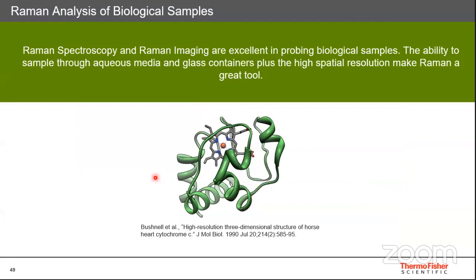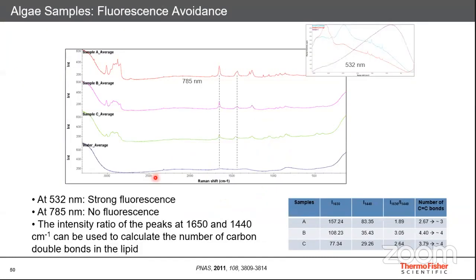Well, it has also been used, as I said, for biological analysis, even if it's an aqueous solution. Here is an example of an algae sample which has shown fluorescence. Here they used earlier the 532, which shows a strong fluorescence. So they have to go to the higher wavelength laser, that is 785. You can see a nice spectrum of the algae samples with no fluorescence at all. And from the intensity of peaks from 1650 to 1440, you can understand the number of carbon-carbon double bonds that are present in the lipid in that algae sample. So from this, they have identified that A, B, C different samples have different numbers of carbon-carbon double bonds in the lipid.